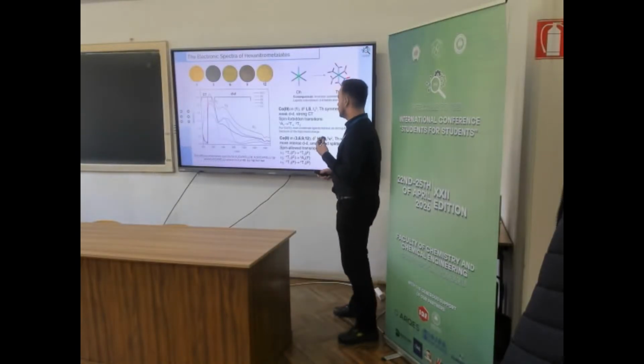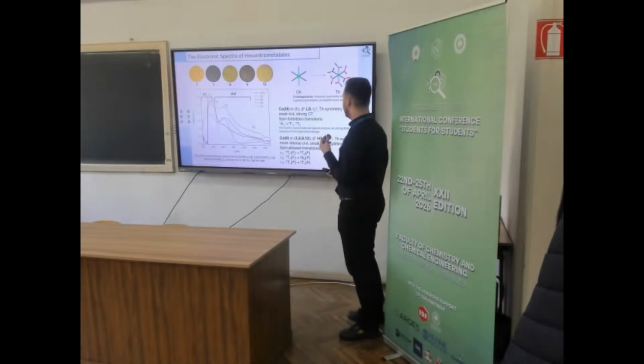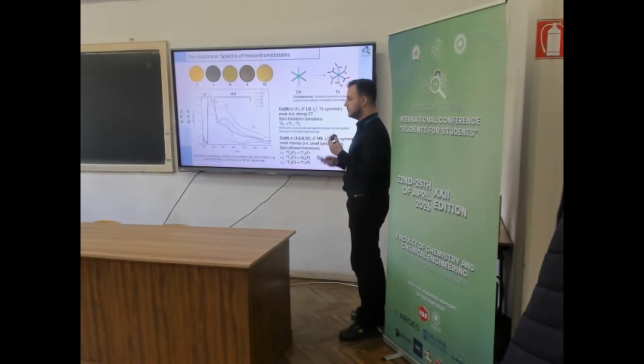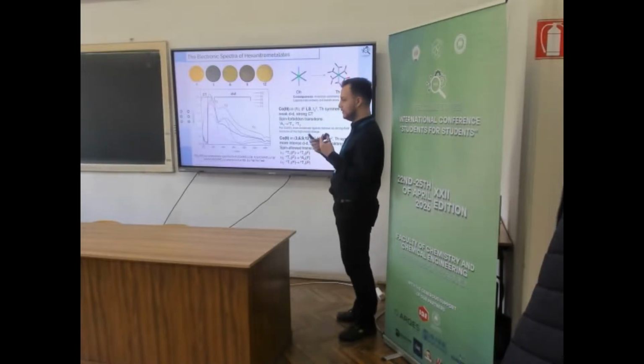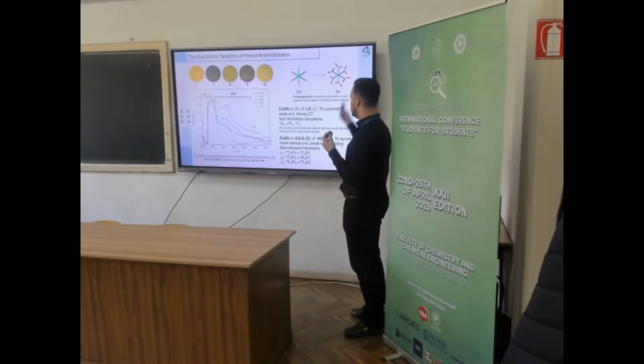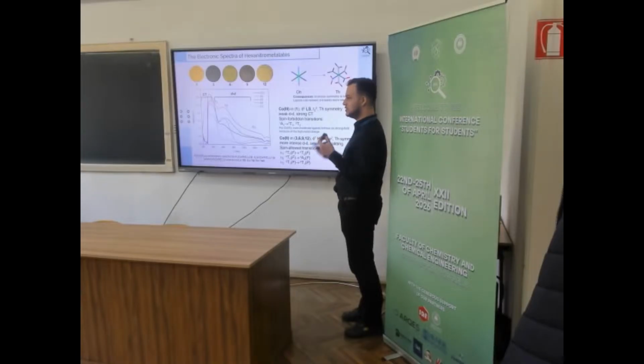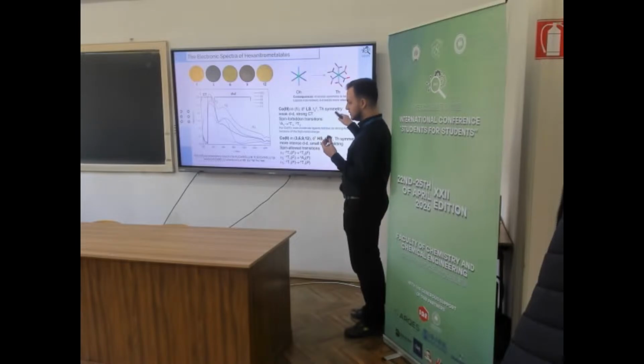Moving on to the electronic spectra, one thing to keep in mind here is that because of the ligands and their interactions with the lattice, the symmetry is reduced from octahedral geometry toward tetrahedral. This causes the Laporte rule to relax, making d-d transitions a lot more possible. This effect intensifies further with counter ions.